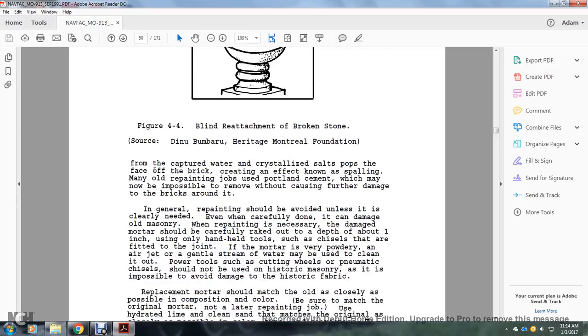All right, from the trapped water, crystallized salt pops out of the face of the brick, creating an effect known as spalling. Many old repointing jobs used Portland cement, which may be impossible to remove without causing further damage to the bricks around it. In general, repointing should be avoided unless it is clearly needed. Even when carefully done, it can damage old masonry. When repointing is necessary, The damaged mortar should be carefully raked out to a depth of about 1 inch, usually only with hand-held tools such as chisels that are fitted to the joint.